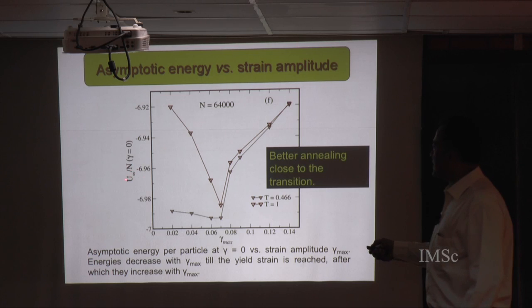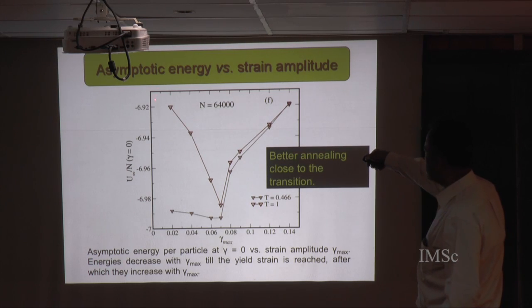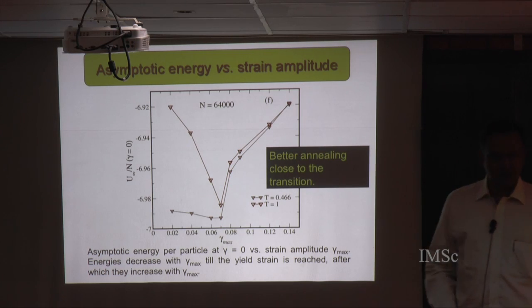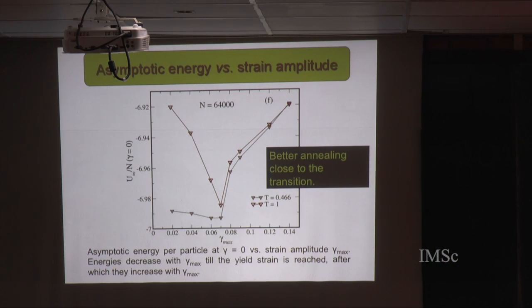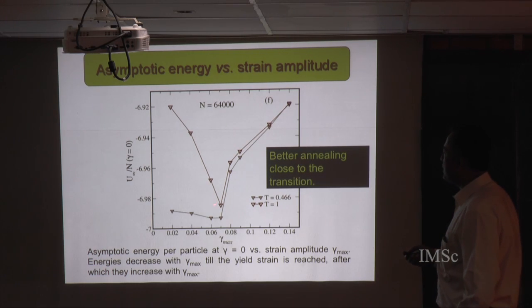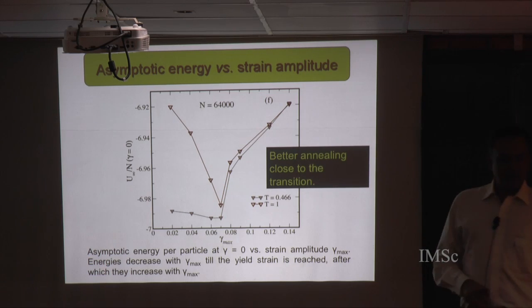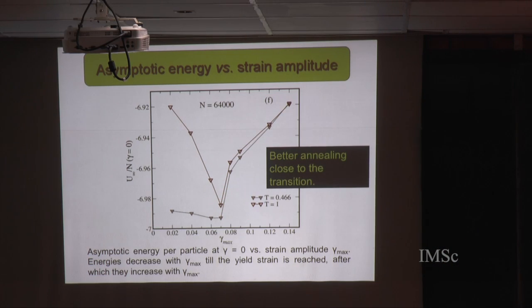So here is this energy asymptotically as a function of strain amplitude, and you see these energies show a clear minimum at the transition. One of the upshots of this analysis is that the lowest, or most annealed, glasses are formed right at the yielding transition. It's something interesting. Of course it takes a long time, so it may not be of practical value, but it's interesting to see.